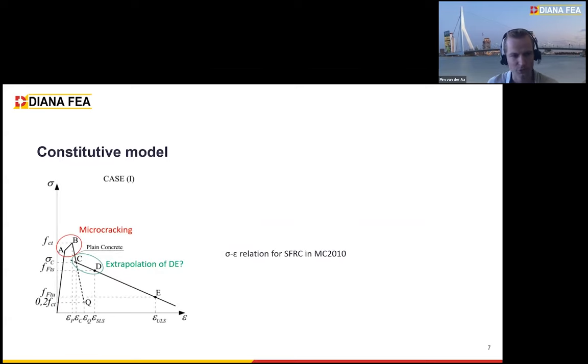If you now continue to the stress strain relation, which is in the model code, it's basically built up partly as plain concrete, so the first branch up to A, B, C, and then Q is just plain concrete. As discussed before, we recommend not to include the A, B branch. The other thing I would like to talk about is the branch between C and D.